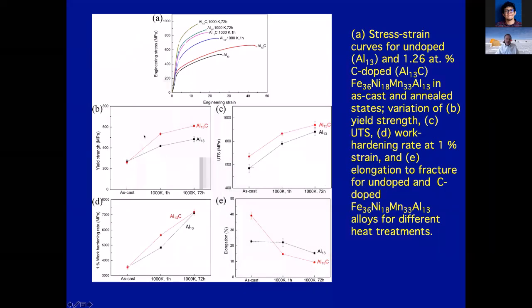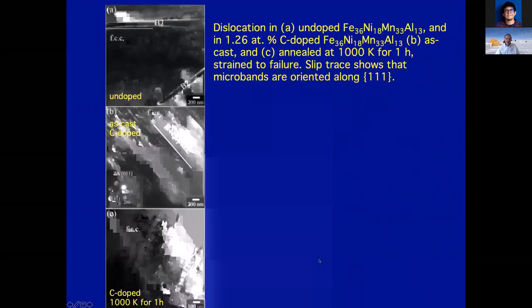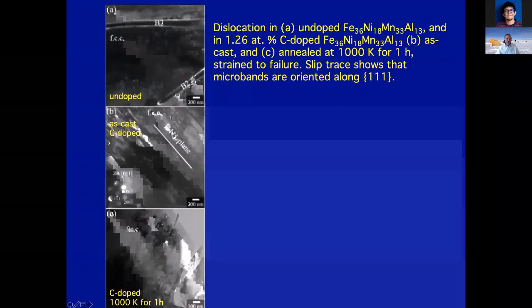So this shows the yield strength as a function of the heat treatments that I showed in the microstructures before. So the as-cast materials, with and without carbon, surprisingly have very similar yield strengths. This is all the data up here, just summarizing these graphs. As we heat treat it for an hour at 1000, the strength goes up because we're now producing those extra precipitates in the matrix. And as we anneal it further, we get more precipitation in the matrix, and so the strength goes up. But unfortunately, the ductility goes down pretty much, particularly in the carbon doped material. And this just shows the dislocation structures after very large strains. And again, we get microbands in the FCC phase in this material.